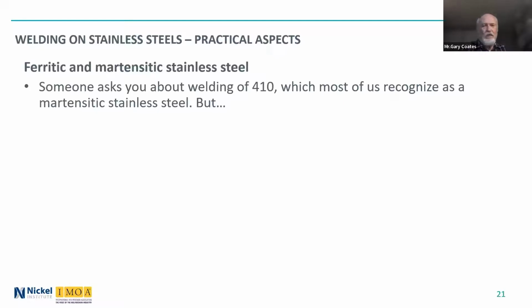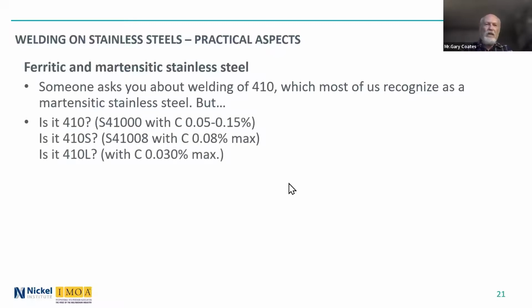And you know, the first thought is, well, 410, that's a martensitic stainless steel, but is it? Is it 410 with the actual higher carbon version of 410, which can have as high as 0.15% carbon? Or is it 410S? That's a more weldable grade used in plant construction, which has a 0.08 carbon max. Or there exists a 410 low carbon version, which has 0.030 carbon max, just like a 304L or 316L.